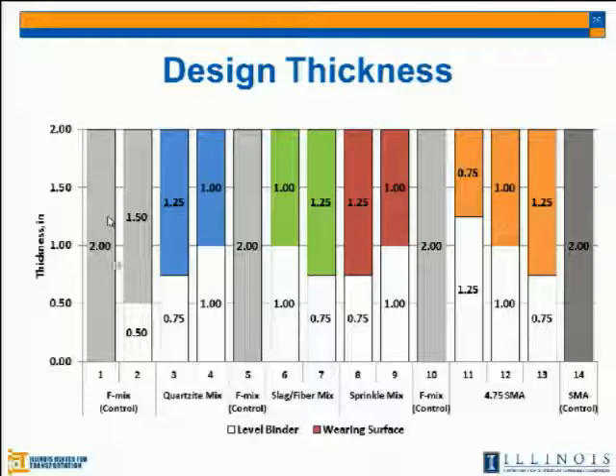But if we place the 2 inch wearing surface, we didn't have the leveling surface here. But if we have the 1 inch wearing surface, we place 1 inch of leveling binder. So the total is 2 inch. The leveling binder is a kind of cheap material. So if we reduce the wearing surface thickness, the cost will be cheaper than the other section.